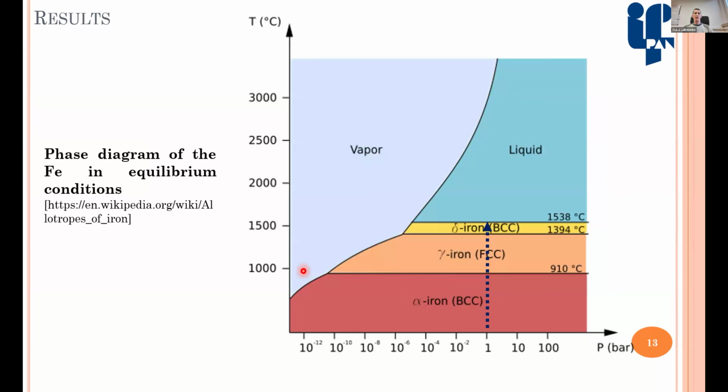And what do we expect to see for iron? We are starting from alpha iron with a body-centered cubic structure, and looking at the conventional phase diagram, we are moving through the gamma iron region with a face-centered cubic structure to body-centered cubic delta iron, and we are near the melting point for the presented data. And what is the origin of the low Q peak?